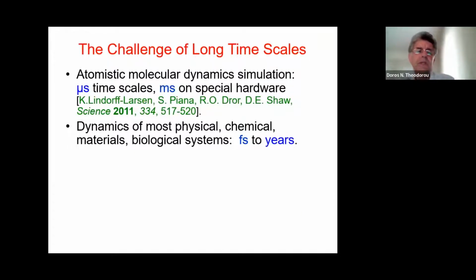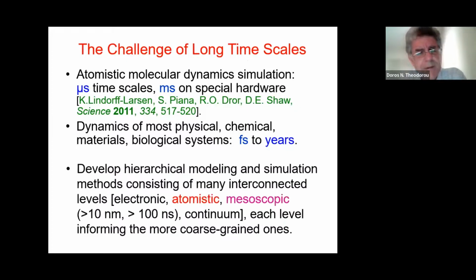By comparison, if we consider atomistic molecular dynamics, which is the most common simulation method to predict properties, this can go up to microseconds on ordinary Beowulf clusters, for example. It can go to milliseconds on special hardware, but it can certainly not address these very long times that we encounter in polymers. What do we do? We try to develop hierarchical modeling and simulation methods, which consist of many interconnected levels: electronic, atomistic, mesoscopic, and continuum, each level informing the more coarse-grained ones, so that in the end we may be able to connect the chemical constitution to the macroscopic properties.